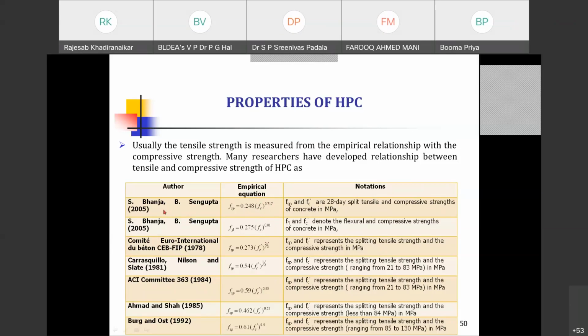not reliable values. So this one, Sengupta: split tensile strength = 0.248 f_c^0.717. f_sp is the split tensile strength here, and f_c' is the 28-day compressive strength. Almost the same, Bhanja, in 2005, and then CEB-FIP in 78: 0.273 f_c^(2/3), and Carrasquillo-Nilson, this is 0.54. This was basically done for high strength concrete long back in 81, and it worked well up to 80 MPa, but beyond that it doesn't work better.